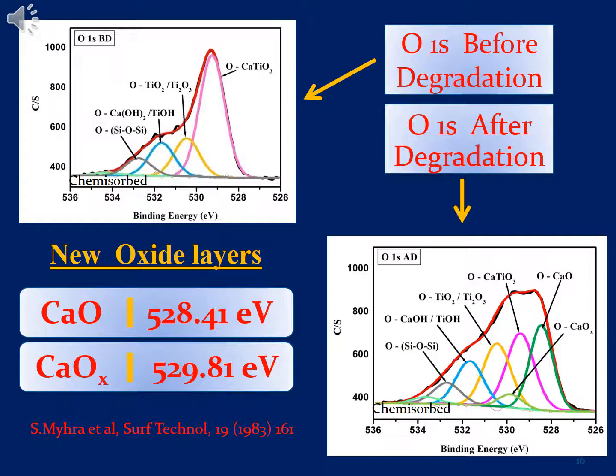I see from the oxygen peak a major contribution which is coming from calcium titanate, which is the major material on the surface. And I also have some suboxides which are forming. I have Ti, which is possibly unreacted titanium from when we were preparing the material, and I also have some calcium hydroxide as a result of water vapor attacking the surface, and I have the rest of the species.